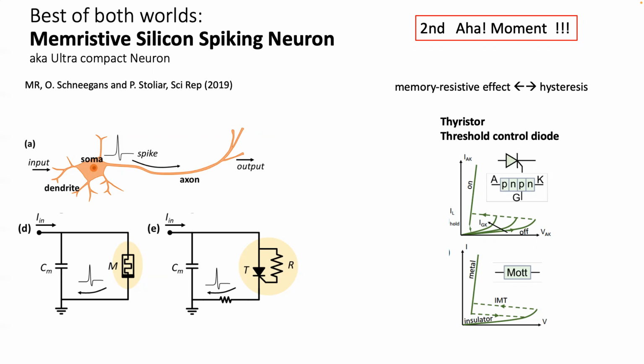The interesting part is that here you have two diodes, one after the other, so you would expect this to conduct. But then there is an NP junction there, and that junction is in inverse, so it doesn't allow the current to be conducted. That's why when you put it in direct, the thyristor still does not conduct current and has a high resistive state. But it has a threshold, and that threshold is when you push it beyond a certain applied voltage, or you can control it through the gate, where this depletion layer becomes filled, and when it becomes filled, the device conducts, and the system has a very strong transition from a high resistive state to a low resistive state. But the key insight, besides that, is that this system has hysteresis.